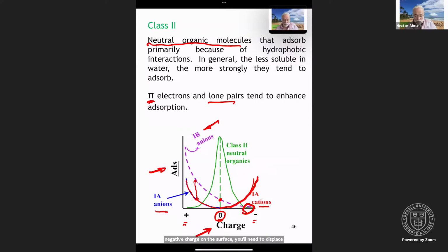And then finally, the neutrals. At zero surface charge, you have a maximum because that's when the electrostatic repulsions are minimized. If you go either positive or negative of that, then you see a typical profile like this going to zero. So at significantly positive or negative surface charges, organics really don't want to be there. However, when it's neutral, then you have a high propensity for these species to adsorb.